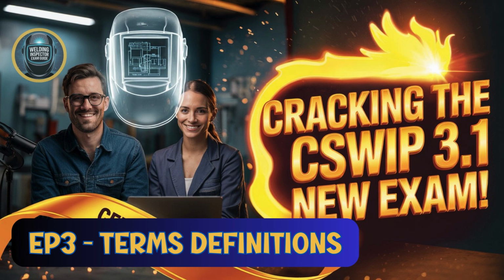Sounds good, but is there a catch? There is. It requires very careful control, specifically a very constant high travel speed during welding. If that speed varies, you significantly increase the risk of solidification centerline cracking right down the middle of the weld. So higher productivity potential, but also higher risk if not done perfectly. I can absolutely see why concave fillets are preferred for fatigue-sensitive applications. It's all about spreading that load and avoiding sharp corners. That's the name of the game for fatigue, yeah.